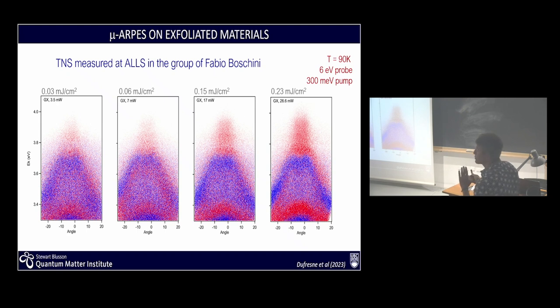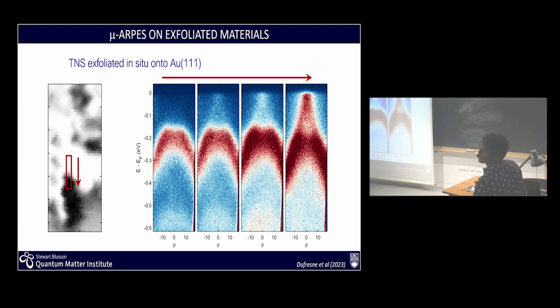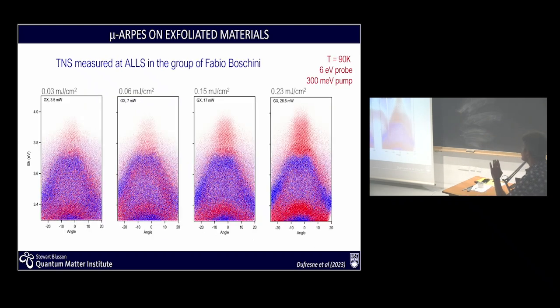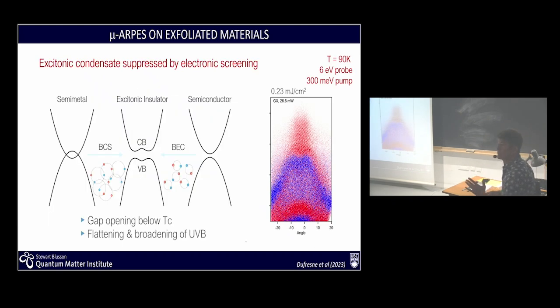And what we see here is in a different spectra, so pump, no pump. Blue is depletion of population, red is increase of population. We see that as we increase the fluence, still at very small fluences compared to the 1.6 or so millijoule that I showed you before, you go from an insulating state all the way back to a metallic state, which is pretty much the same as this one done through surface gating. So we have two ways of quenching the condensate electronically: through surface gating, or through very delicate pumping resonating with the gap. And in both cases, we are back to a metallic phase.